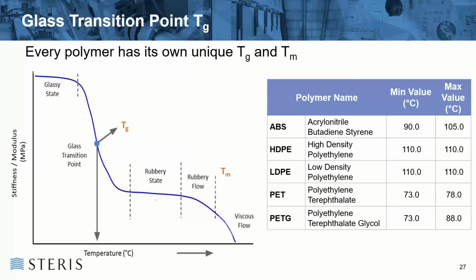If you look at, say, typically the PET or PETG there on the bottom of the table on the right, which is the lowest typical temperature for a material, you're looking there at between 73 and 88 degrees for this product. And if you're getting up around that temperature with your aging, you're actually going to destroy the package or the product, whatever this material is actually incorporated into.